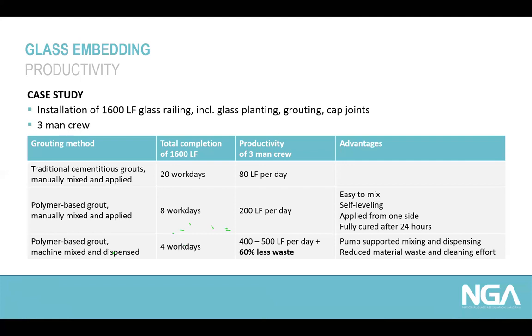And here those experts saw the advantage in the easy mix and self-leveling of the product, and also that it could be applied from one side and it leveled to the other side of the base shoe. They didn't need to have access to the other side. They also confirmed the full cure of the polymer-based system after 24 hours, and then it could already be covered with a sealant cap joint.